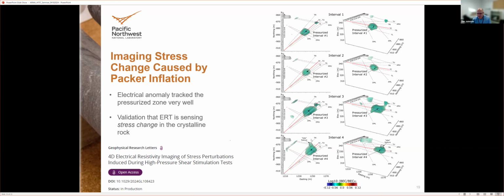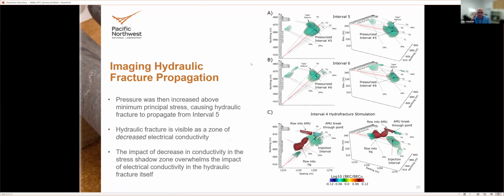And we hydrofractured this later, and I'm pointing out this feature right here, and these ones deeper in this well, because when we hydrofractured in this zone, the hydrofracture ran right through here. So there was this more compliant zone suggested here that actually fractured later when we pressurized that interval and made the hydrofracture. So that's shown here. These are just more of the hydrofracture or shear stimulation test where this lobe develops. And then here is where we actually hydrofractured it.